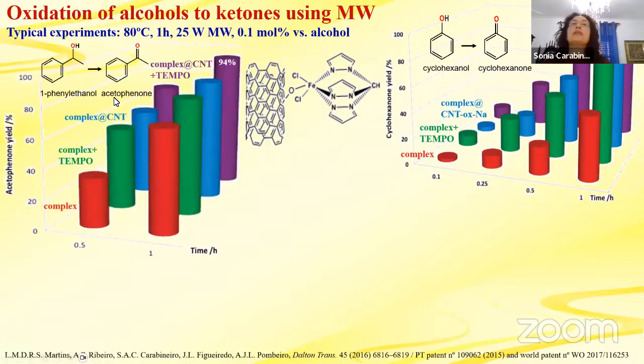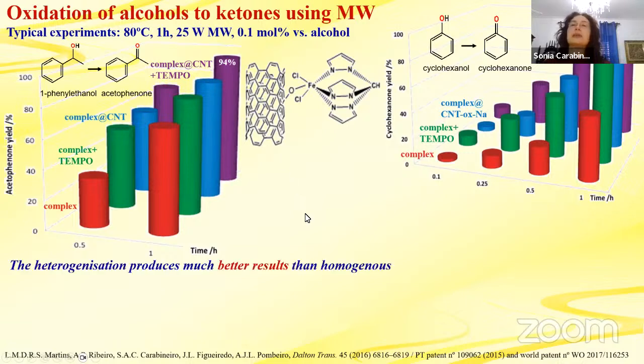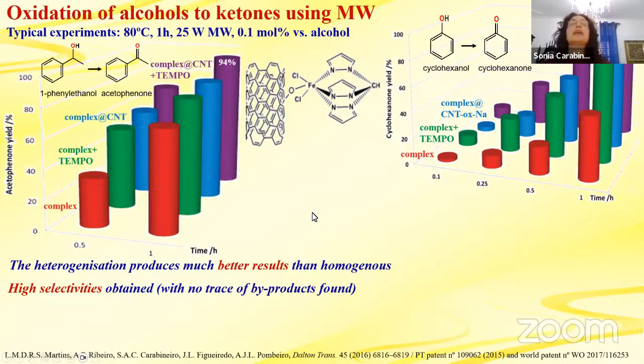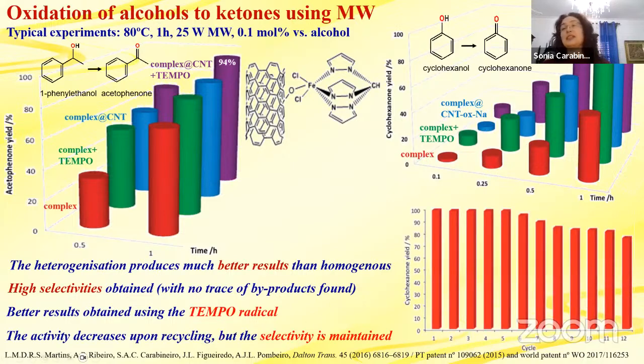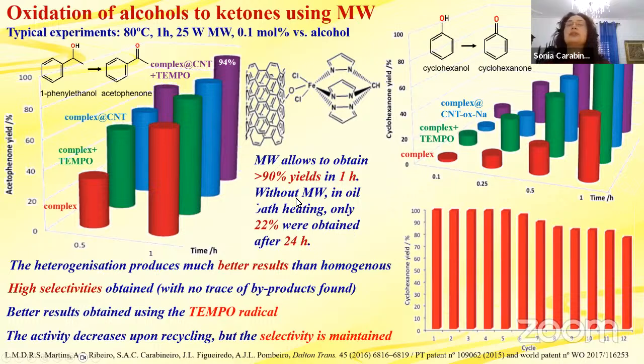We also tested for 1-phenylethanol, okay, and the same trend, and the best result was 94%, okay, for this complex. So we see heterogenization is also much better. We also obtain nice selectivities, no trace of byproducts, and better results with the tempo radical. And if we do a recycling, we could do it up to 12. We did it up to 12 cycles, and there is a small loss of activity, again, due to leaching. It's difficult for that not to happen.